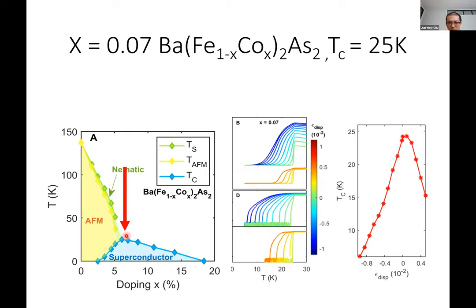Yeah, this is a very good question. And yes, we have some studies, but we don't have any conclusive results yet. One difficulty is that once you're applying strain, it's basically anisotropic. And how do you define the power law in this sense? Most of the time, people consider the power law of resistance in the overdoped case where things are isotropic. But here we actually have an anisotropic resistivity tensor. Of course, you can take the average of the resistivity to compare.